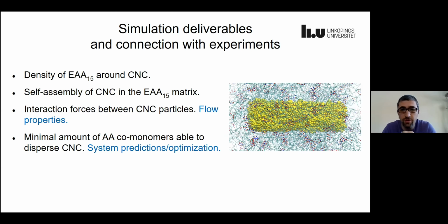And what we are aiming to achieve in this project, and how in general we can connect these simulations with the experiments, is, for example, as I said, we can look into the detail and into the microscopic picture of these materials. And we want to see what the density of this polymer is, for example, around the CNC, and what the surface interactions are between the CNC surface and the polymer. We also want to see how these nanocrystals can self-assemble in the EAA matrix, because this is a very important question in order to understand these materials. And also, for example, we can measure very accurately the interactions between the individual fibers, crystals. And this also can be connected to, for example, flow properties which you measure in the lab.